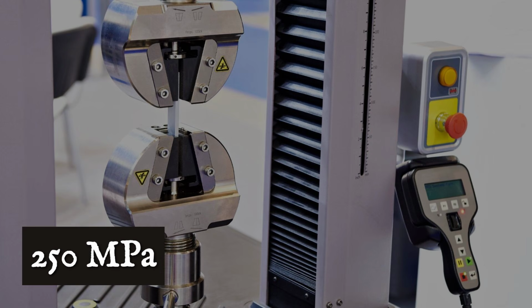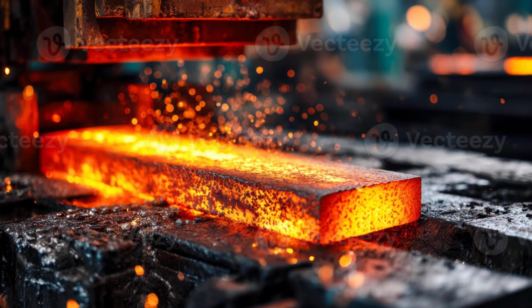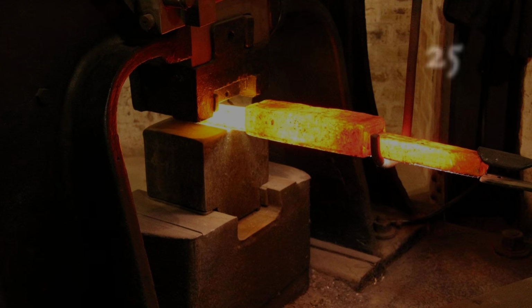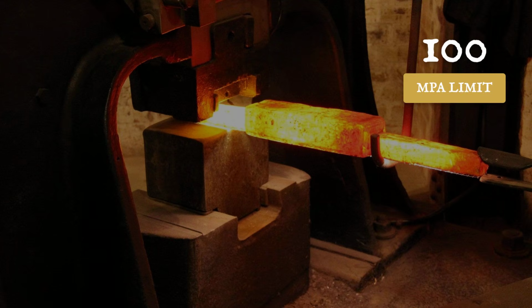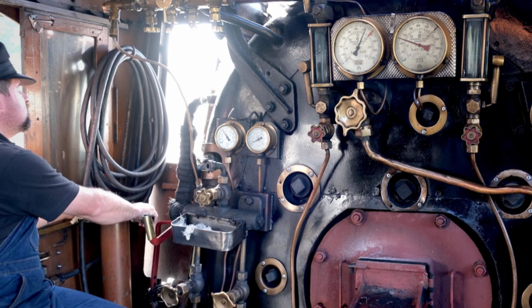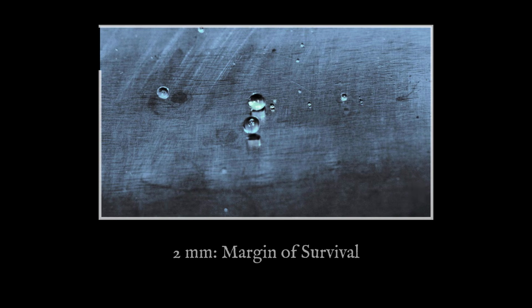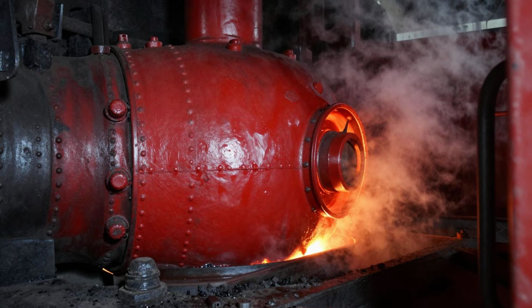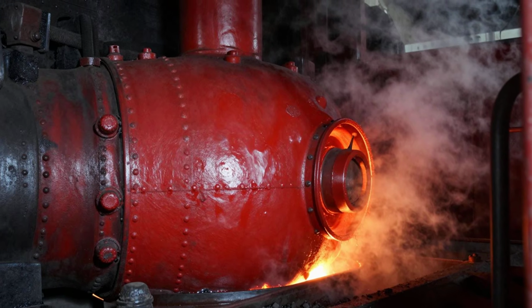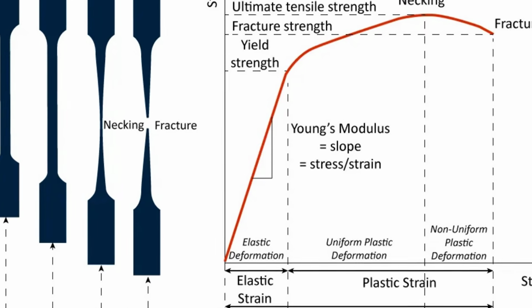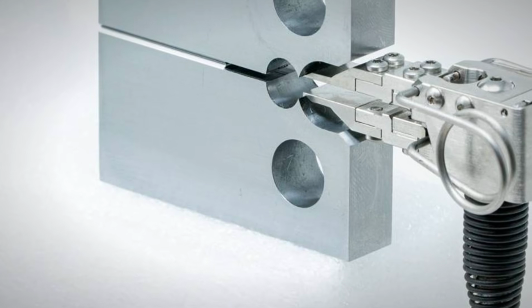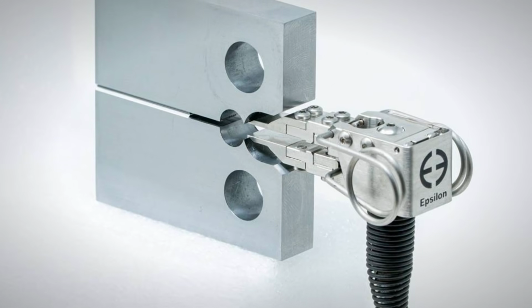Room temperature boiler steel might hold at 250 megapascals. Heat it to 550 degrees Celsius, and that limit collapses to under 100 megapascals. The margin is gone in a blink. If the water film thins to less than 2 millimeters, the crown sheet temperature surges. The steel stops behaving like a solid. It starts to flow. Plastic deformation sets in. The plate stretches under load, then fractures.